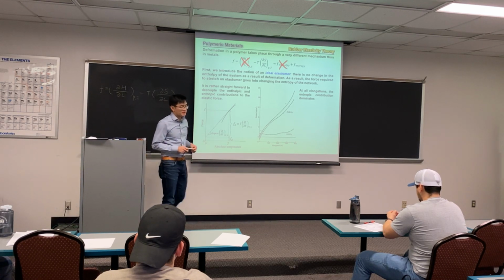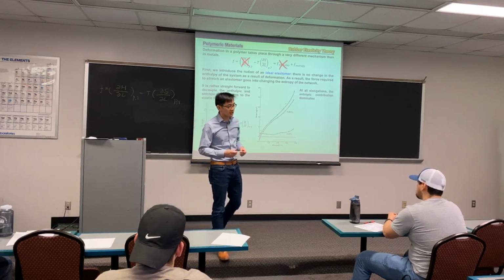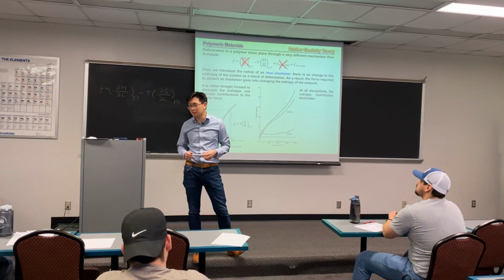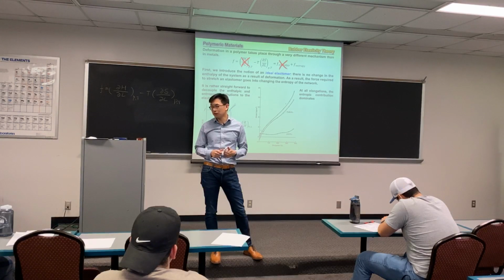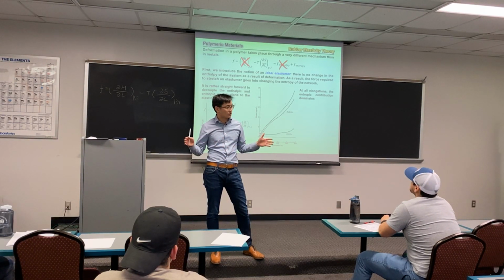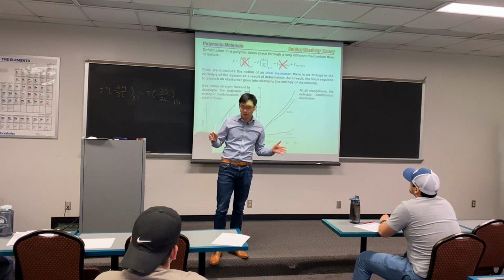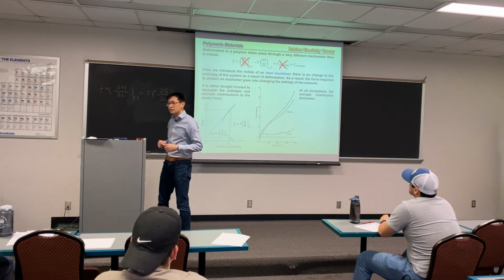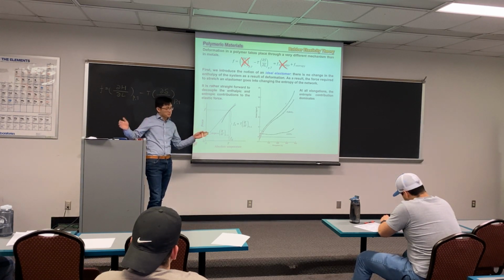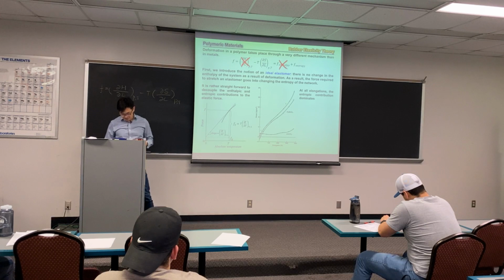So for simplicity of discussion today, let's come up with a concept called the ideal elastomer. We also assume your deformation at the molecular level matches the macroscopic one, which is called the affine model. So your local distribution will match your global changes.